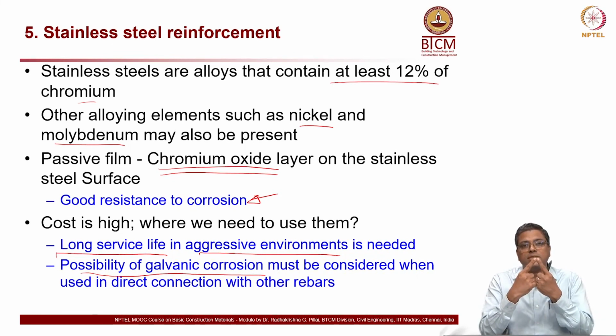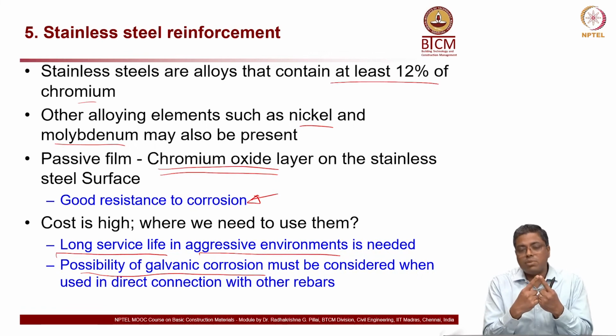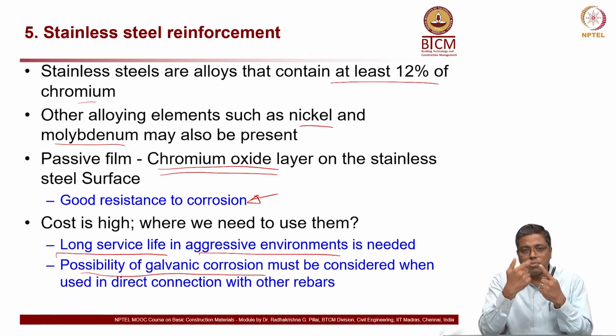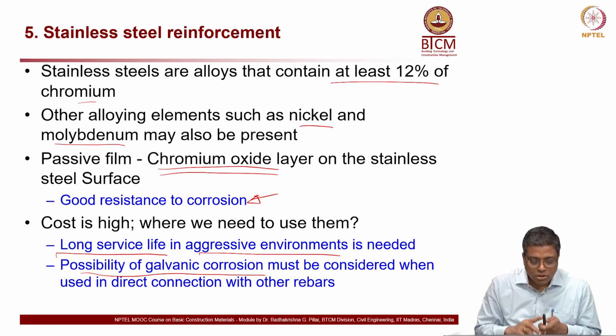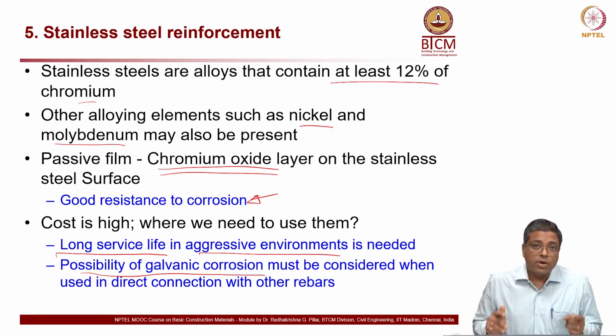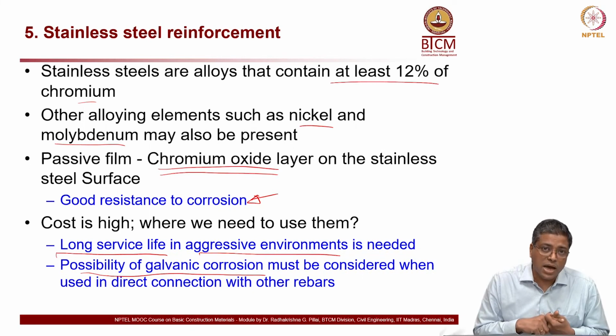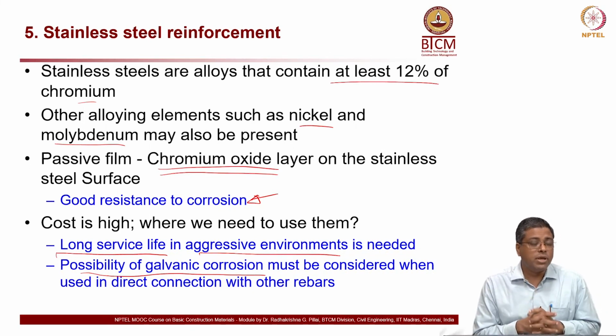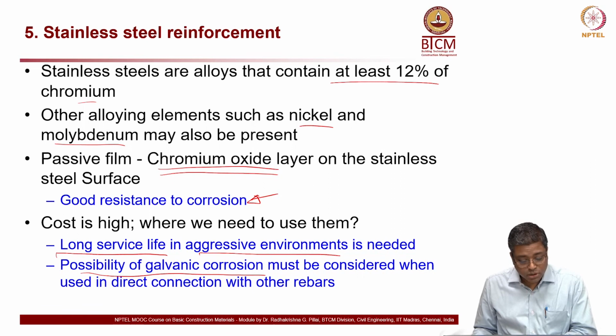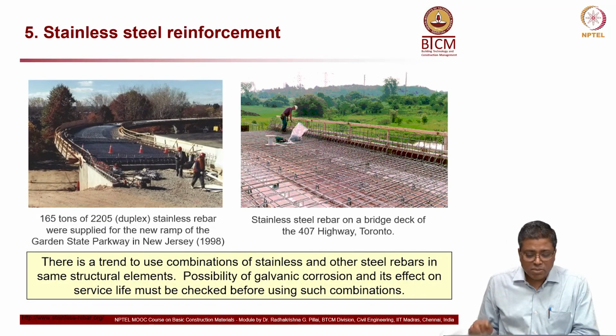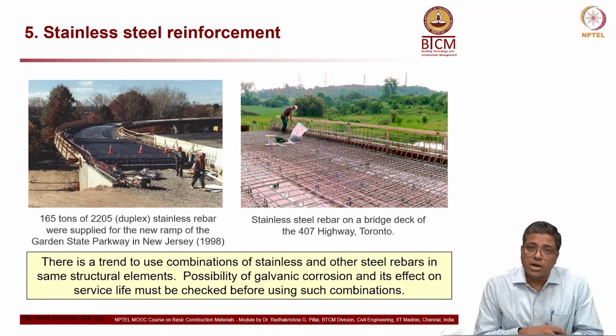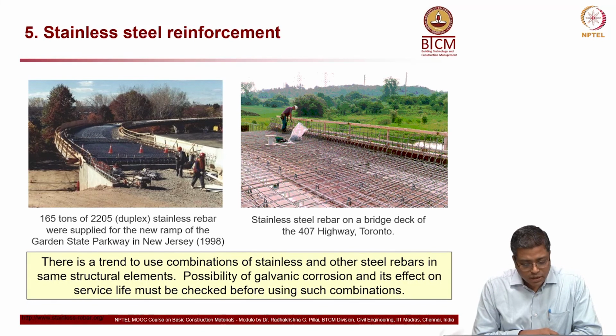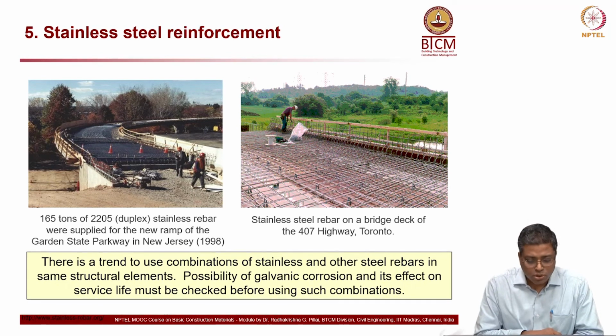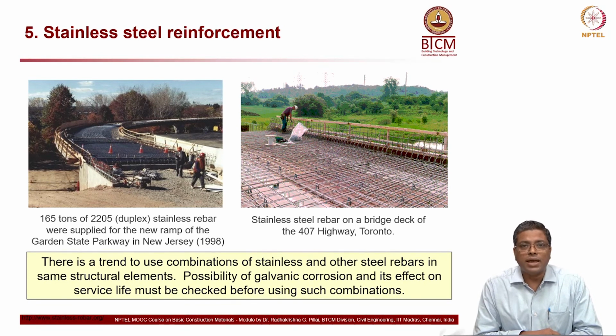So when two dissimilar metals come in contact, a battery will form, and that will cause galvanic corrosion. So when you put stainless steel in combination with other steel, you must check whether there will be galvanic corrosion or not. That's something important to check. These are some examples where stainless steel rebars have been used for bridge construction. But in India we don't use it much, because these are in Toronto and New Jersey, very cold climates where they have severe chloride.